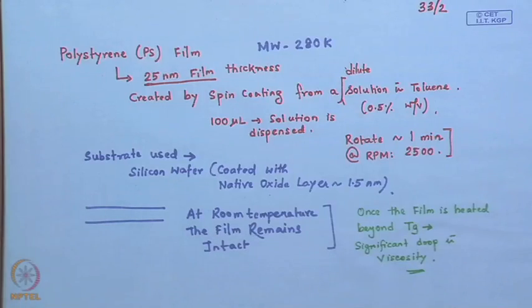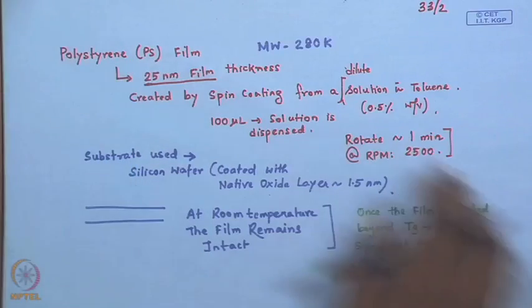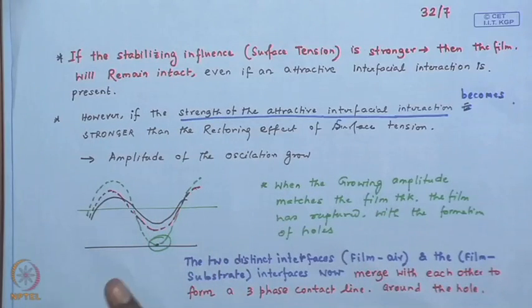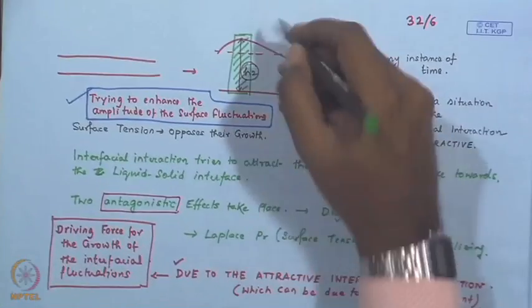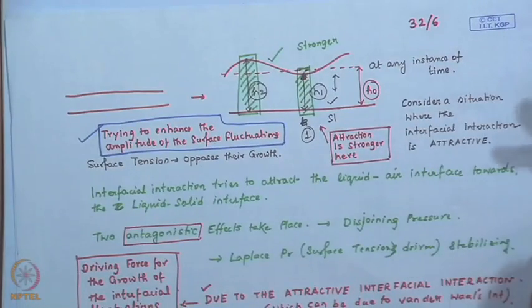However, once the film is heated beyond glass transition temperature and the viscosity has dropped, the film is now more in a liquid form. So, these fluctuations now manifest at the surface, and depending on the nature of the interfacial interaction, the film-air interface is now in a position to deform to the magnitude of the interfacial forces. While talking about the AFM, we also picked cantilevers soft enough that they deformed due to the interfacial forces. Essentially here also the same thing happens. Once the film is in a liquid form, it starts deforming to the interfacial forces, and then the fluctuations can amplify and grow.